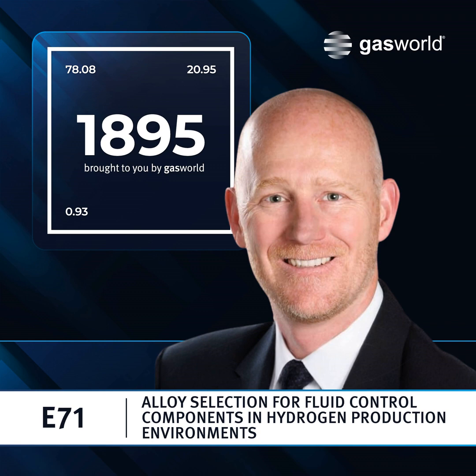In the actual process environment, in these large vessels with these nickel radiant tubes, the high temperature environment and the elements in the environment can cause damage called metal dusting, or you can also see oxidation or creep-assisted cracking. And being able to use these fluid control components to sample those gases and understand the content, the sulfur and carbon content, for example, allows you to determine when you may want to purge the system with nitrogen or steam, and that allows for improved life of the component. So it's really critical to the cost-effective operation of these things.